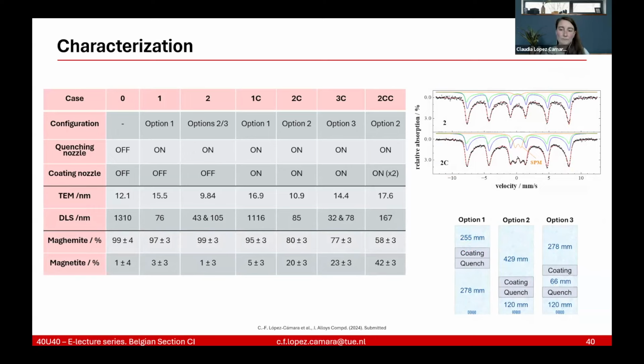And the most important part that you have to notice is that you get this sort of double peak that shows that you have superparamagnetic activity. So based on that, we saw that we did have maghemite and magnetite phases in all of the samples, and only those two phases, there is no other iron oxide phase on any of the samples.